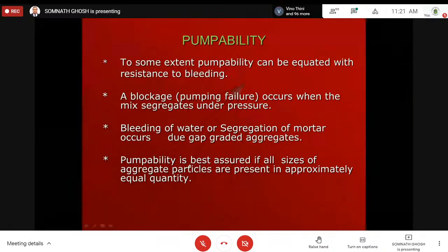Now you see, you will be able to produce a very good pumpable concrete if all the sizes of aggregates are present in the concrete more or less in equal quantity. I'm not saying exactly equal quantity, more or less. That will give you packing, and you will be able to achieve cohesiveness through the use of viscosity modifying admixtures. You can reduce the water-cement ratio by using high range water reducers. So all these things you can do. Keep this in your mind.